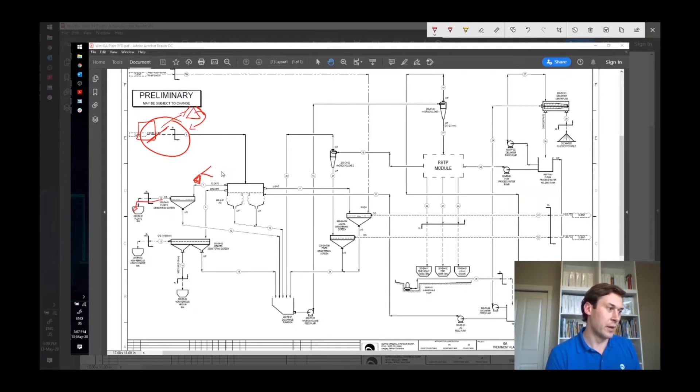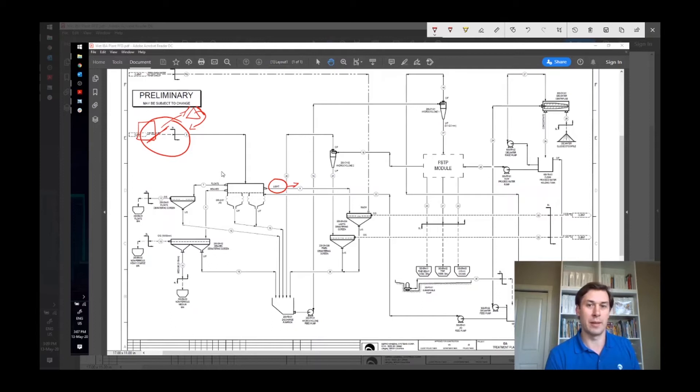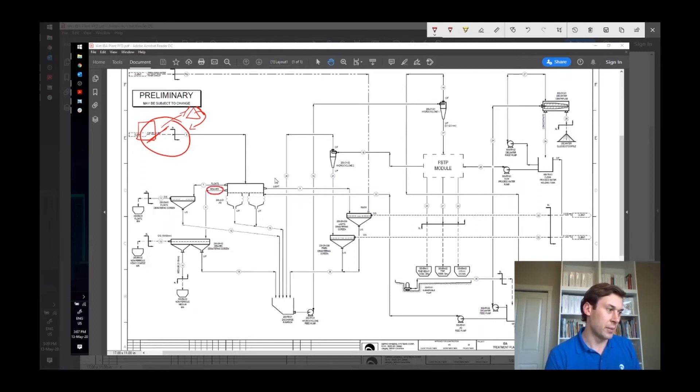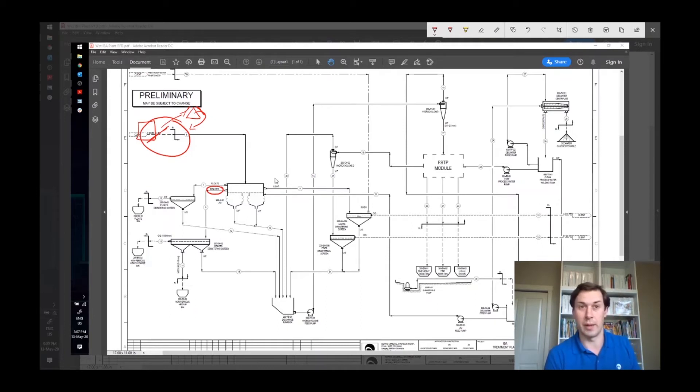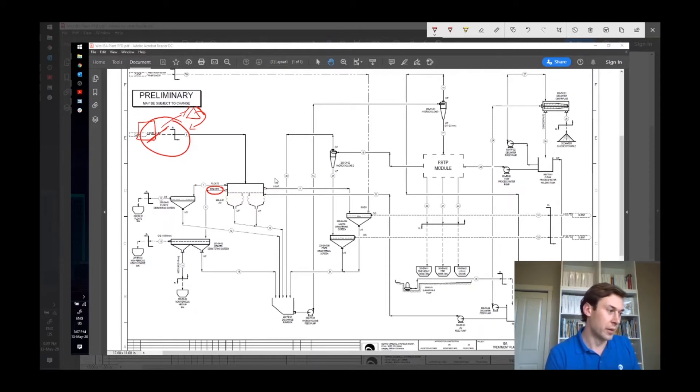The next thing we have is we've got a light stream. And so this will be the lower density material, the slag, the mineral, glass. And then we have the heavy non-ferrous that comes out here, so this will be the sink. So anything that's higher density than the mineral slag fraction, and this should be basically all the heavy non-ferrous.